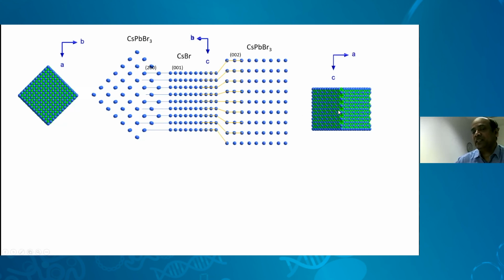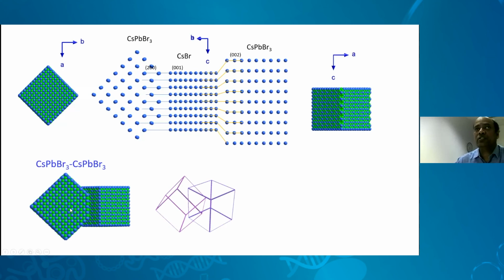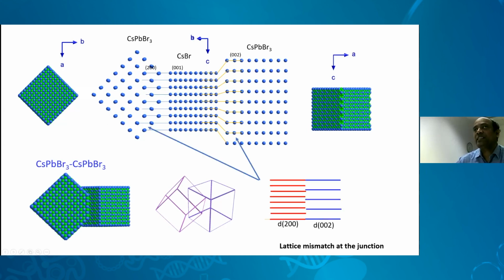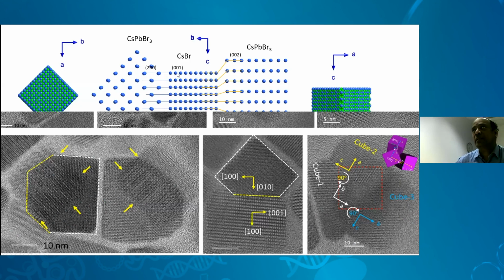As a result, you get these beautiful structures. These two structures are connected, same materials, but they connect like this. So that's how the two cubes are, one is tilted, one is the normal standard cube. But interesting, same material, but you see the lattice mismatch at the center because their orientations are different. So you can see these beautiful TEM images, how these are connected. You can see here two cubes. This is the tilted side. This is the standard cube with the orientation.